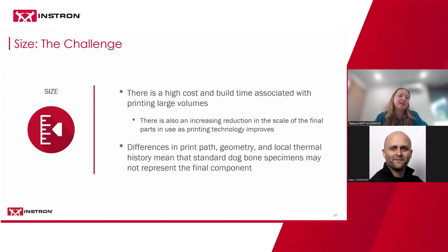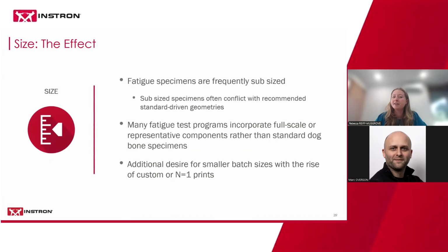And then beyond that, when we consider size, we consider the size of a sample. What we know is that differences in print path, geometry, and the local thermal history are caused by often different sizes. As I mentioned, something large dissipates heat more slowly than something small. We often find that standard dog bone specimens might actually not represent the final component in terms of its thermal history and mechanical properties. So the effect of this, if you haven't guessed already, is that fatigue specimens and mechanical specimens in general are frequently sub-sized when we look at additively manufactured specimens. These can often conflict with recommended standard-driven geometries. It's often difficult to print enough material for that.